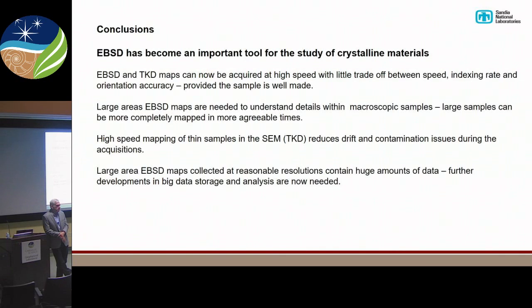Anybody else? So I noticed that now the resolution is about 10 nanometers. So can you resolve the crystal defect in your technique? For example, individual dislocation. You can see, I'm pretty sure you can see the subgrain boundary, but how about the individual dislocations? There's been some recent work, look up the papers by Angus Wilkinson and Ben Britton, where they're starting to push the technique, the strain analysis technique, to that point where you're starting to look at single dislocations and look at the distortions around a dislocation in metals.